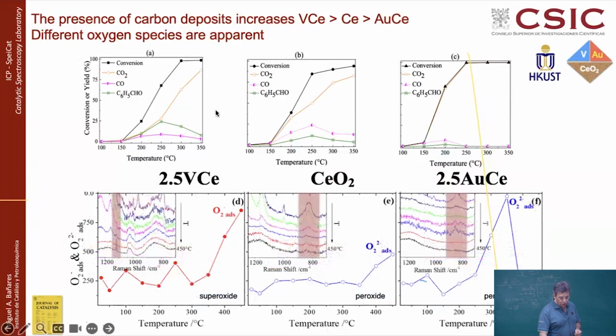We are also dealing not only with the hydrocarbon species, but also with the oxygen species. We have seen that on vanadia ceria, at very high temperatures, you see the presence of superoxide species, whose presence increases at high temperature once the surface is rid of the hydrocarbons. But this is basically telling you that it's not a reactive one, it stays there, nothing happens. However, ceria and gold ceria are showing the presence of peroxide species, which are more reactive, typically associated with the so-called reactive oxygen species. It's really something that you observe for ceria and gold ceria, and that can be associated with a much better combustion of toluene on these two catalysts.